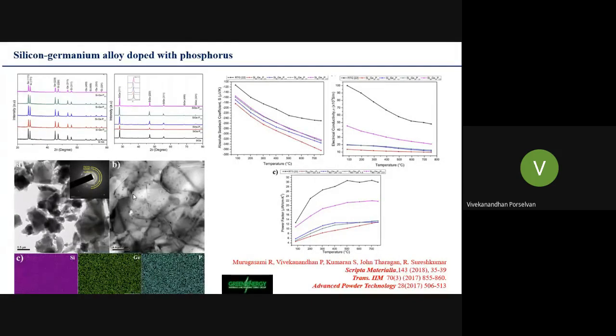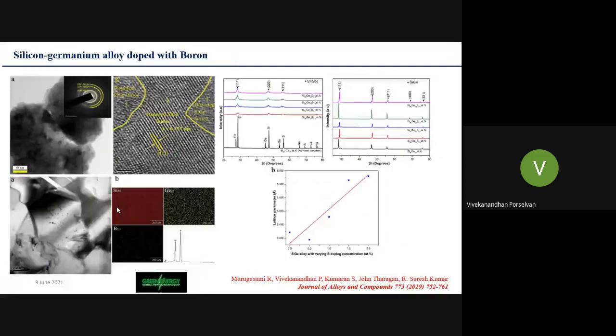This particular alloy was developed through a method called liquid phase sintering. This liquid phase sintering was carried out inside a spark plasma sintering instrument. The liquid phase is sintered in the spark plasma sintering method. And to synthesize this particular alloy, it took some 12 minutes.